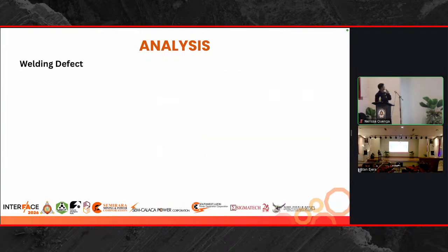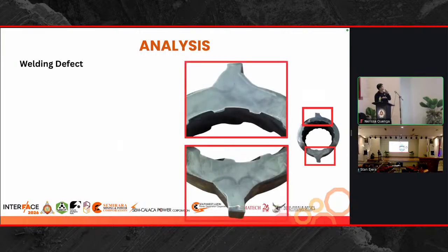Okay, so another thing is the welding defect. This is more on the processing side of the component. Here we have a ring section of a welded boiler tube. We acquired the microstructure from this part and this part, which are welded. Looking at the zoomed images of these parts, it seems that there is no void or defect observed, but we can observe the interface between the welded parts. We have the base metal, and we can observe the heat affected zone and such.